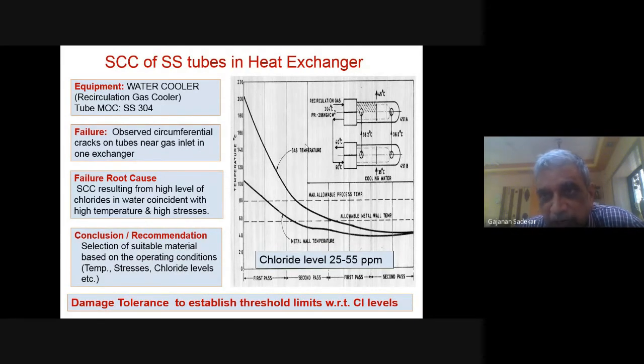So we had a look at the site, and people said, look here, the gas is coming here, going into both exchangers. This exchanger, nothing has happened. This exchanger only has a problem. So after that, I alone stayed there and started studying. And I found that failure has occurred only in a particular zone of the tubes. At the initial period of the tubes where the gas enters, in those first something like 200 millimeters, there was a problem. Cracks were there only in the first 100 millimeters. And a dark surface was there for the first around 200 millimeters. Afterwards, the stainless steel tubes were shining.